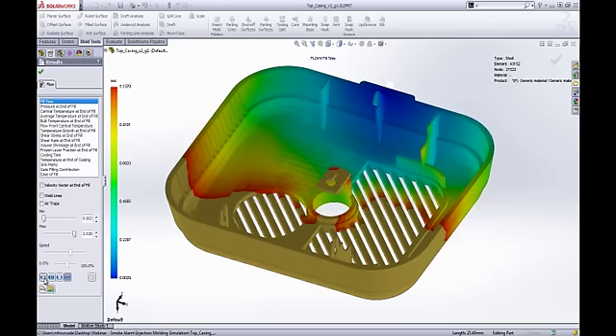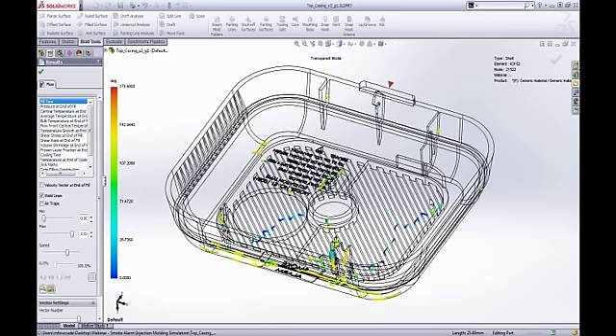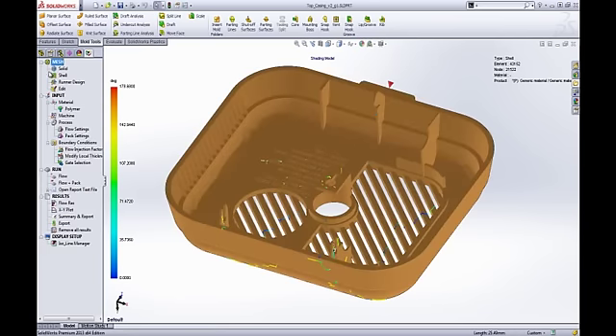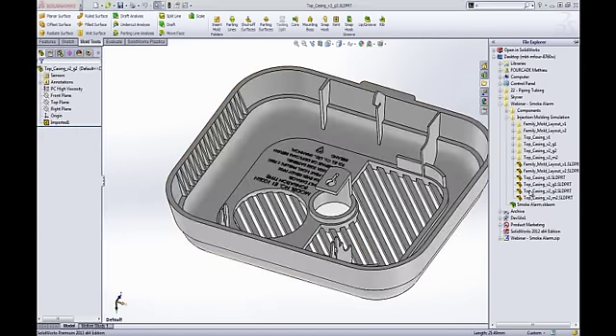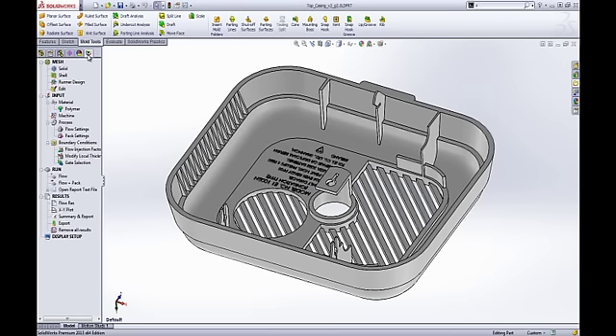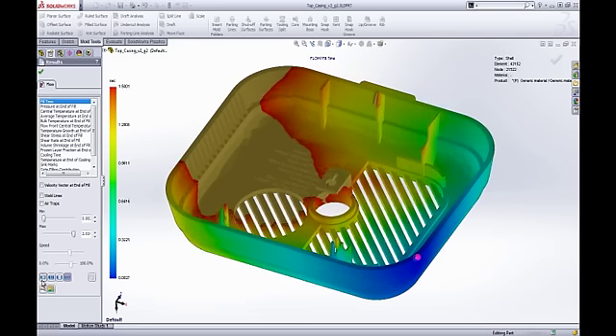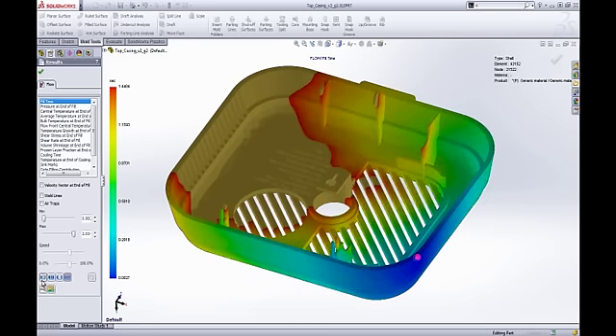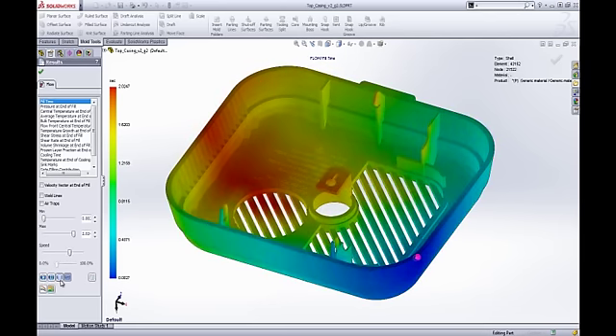The great thing is you can try so many different scenarios before you even produce the part. So we tried with a different geometry, and now we can try with a different gate location. We've prepared different examples so we don't have to run the study again. We switch from having the gate on the top to having the gate on the side. With this new gate location, it's a little bit better because the weld lines are going to be very close to the thick part of the part, so from a structural standpoint it's a lot better. The plastic fills just fine here.